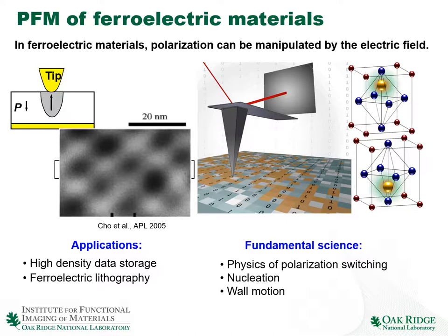So one example that has fascinated the scientific and industrial community for quite a while is the use of ferroelectrics as the recording medium. So imagine that you have a hard disk, but instead of the ferromagnet, it is covered by the ferroelectric layer. You are going to use the scanning probe microscopy tip to switch the polarization up or down, essentially creating the recording where the polarization is used to contain the information. It turns out that initial results in this technology obtained about 20 years ago were extremely promising. So it is possible to create ferroelectric domains of the order of several nanometers, corresponding to extremely high information